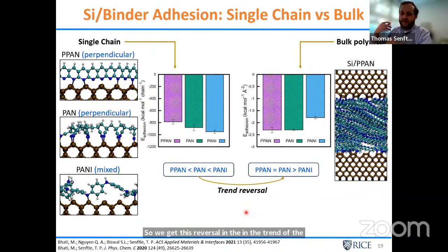And we see that if we run the simulations multiple times and we take statistics to make sure it wasn't just an anomaly based on the way we initially had set up our system, this trend reversal is very robust. Okay, so we see that if we look at the single chains, p-pan binds the weakest, polyaniline binds the strongest, exactly the opposite trend if we look at a bulk polymer at the interface. So, what's going on here?